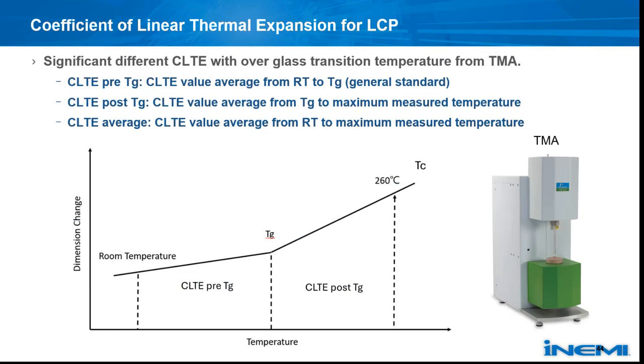Okay, so another factor that may cause the warpage prediction variation is the CTE calculation method. For injection molding simulation, generally the CTE is measured by the TMA and averaged up to the glass transition temperature. However, the slope of measured dimension change shows an upward turning after the glass transition temperature for LCP, as shown in the plot. So if we use the general CTE standard to simulate the warpage, even reflowing up to 260 degrees, this will cause a prediction accuracy issue.